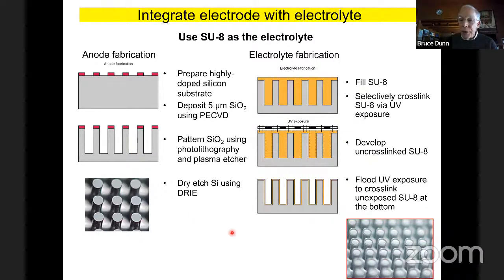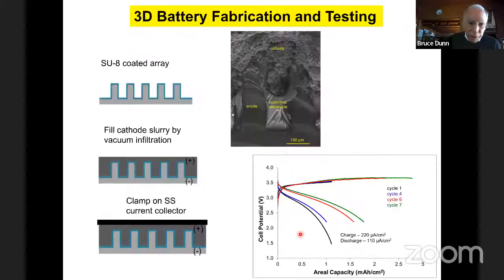Then from there, you're going to use SU8 as an electrolyte. The SU8 is a great photoresist, and it gives you a little bit of conductivity, especially if you're able to integrate a little bit of the electrolyte into it. And so we're able to do that. Again, you go through standard processing methods, and you're able to get these beautiful arrays of silicon covered with about 10 microns of SU8, and you're ready to go. And from here, we work.